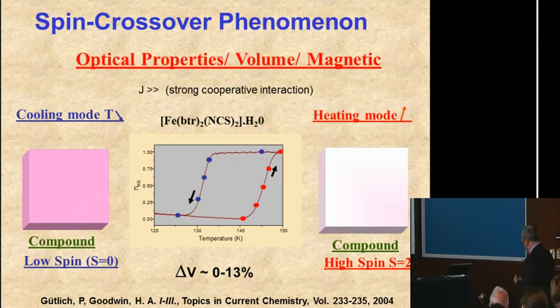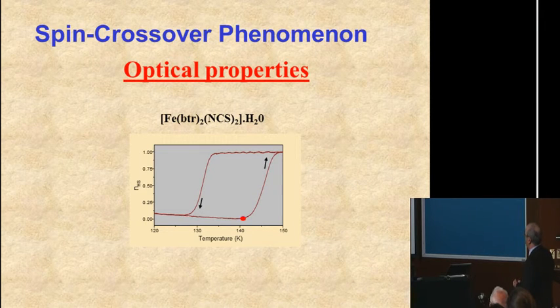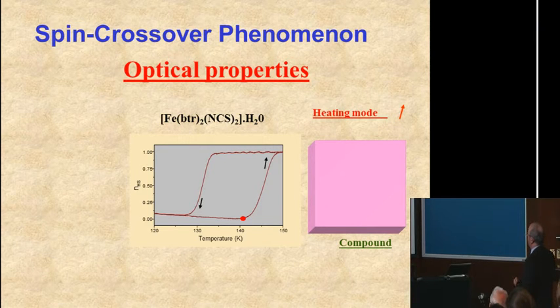So to summarize, we have a strong change of color when you go from the high spin to the low spin form. You have a volume change of 13% and the hysteresis loop of the system. So if you wish to follow the spin crossover, that means that if you prepare your system here within the hysteresis, you can see the color of the system at the macroscopic level. It's pink here. If you increase your temperature, so you are crossing the hysteresis loop, you will see the change of color like that.